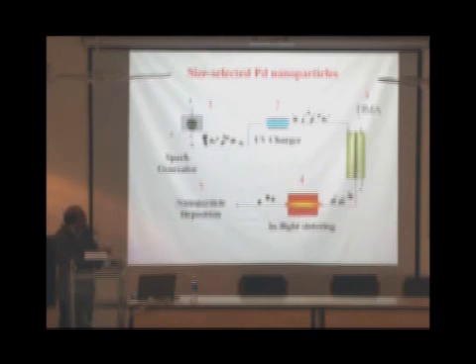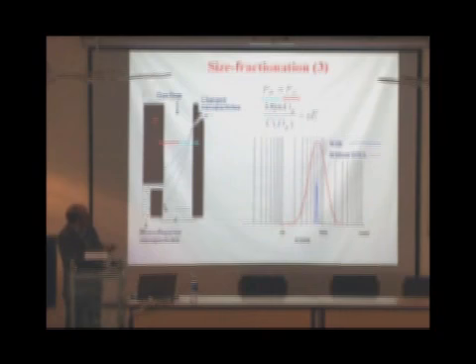These particles are still charged here, and these spherical monocrystalline particles having the same size are deposited onto the substrate. So now we can change the size of these nanoparticles by applying the electric field. We can control the size distribution of these nanoparticles. You can see that if we didn't do any selection, this is the size distribution we would have. This is the size distribution of those agglomerates. And once the selection has been made, this is what we have selected.